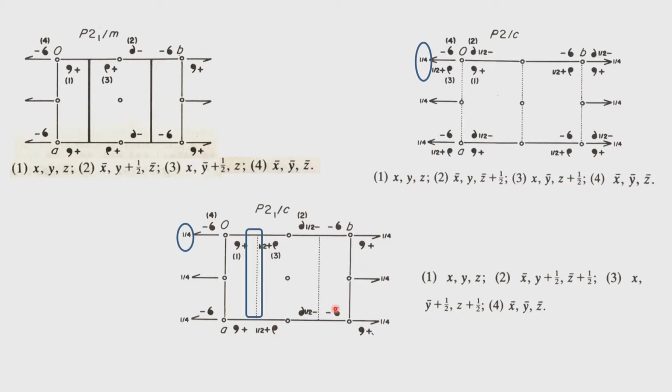Of course the unit cell dimensions now will adjust themselves so that the flexibility associated with the molecule can also be fitted in. If you look at the literature and if you analyze the Cambridge Structural Database and look at how many P21 upon C structures there are, in a recent evaluation it is found that something like 38%, more than that in fact, 38 to 42% I think, of all organic compounds solved so far go into this space group.